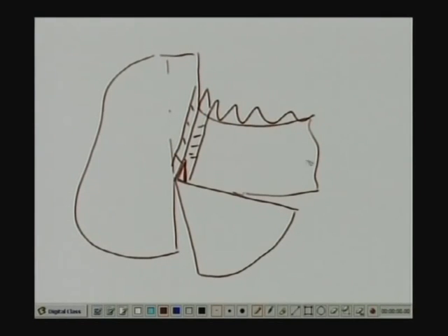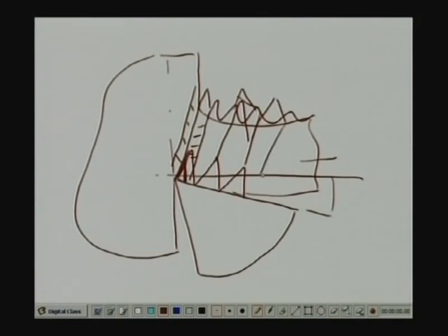Now, when the work material is semi ductile and the rake angle is negative, which is unfavorable, cutting fluid is not given and work material is hard, then this crack goes to a bigger, longer extent, but these are not separated. The chips remain connected, but there is a wide gap. So, this is called jointed chips.